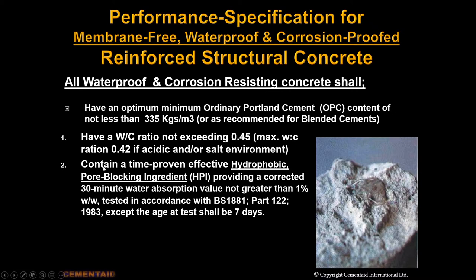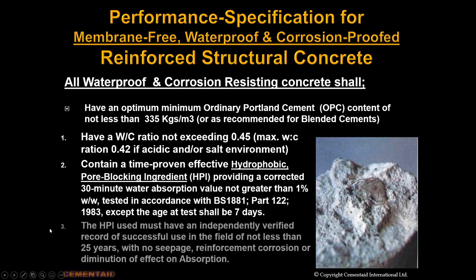It is important here, this particular mix contains a time-proven effective HPI, providing a corrected 30 minute water absorption not greater than 1% tested in accordance with BS 1881, but the test is done at 7 days rather than 28 days. And this is a very important consideration. The HPI used must have an independently verified record of successful use in the field of not less than 25 years, with no seepage, reinforcement corrosion, or diminution of effect on absorption.